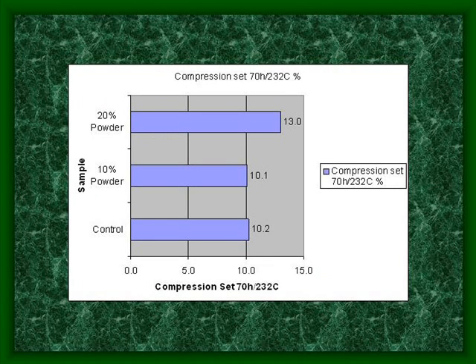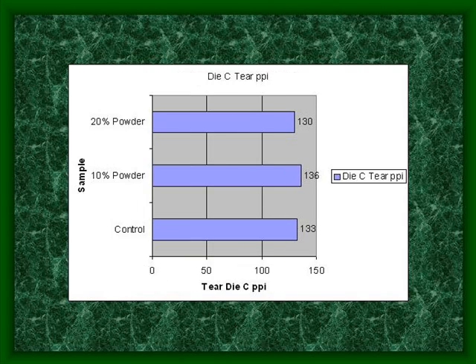Here are the compression set results. The 10% was equal to the control and the 20% only slightly higher. Die C-tear, the samples were essentially equal.